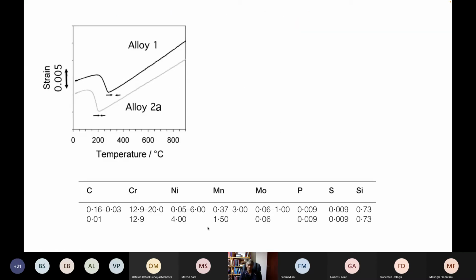So we designed these alloys here. This has a very low carbon concentration, chromium 12%, 4% nickel, so to ensure that it becomes austenitic at high temperatures, and otherwise very, very simple. Now, this is a composition specification, really, that is for martensitic stainless steels, right? But we don't want a very large carbon concentration. So you can see that the transformation happens at a low temperature, okay? Both of these alloys transform at a low temperature, which is exactly what we want. But these are stainless steels.